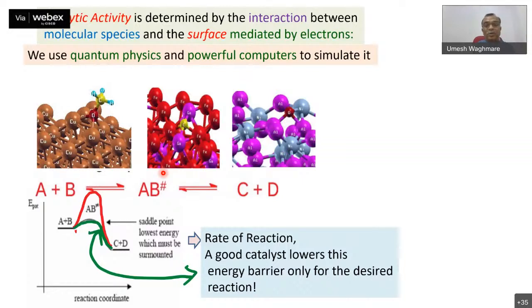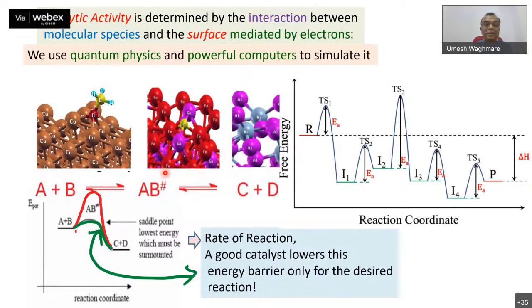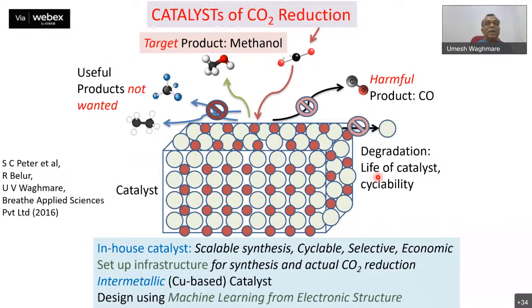This is a very simplified textbook description, but in a real catalytic reaction, there are several steps which go up and down, and from one step to another, one has to go through a transition state. So real analysis is much more complicated, and the catalysis of CO2 reduction is a very challenging problem because you want the target product to be methanol, not other products. One can easily get carbon monoxide by reduction of CO2, which is not a favorable product. One can get other types of degradation of catalytic material because of CO2 and poisoning. One can get methane or ethylene, and none of these are desirable because we want a single product, methanol, and that's what is called selective synthesis of methanol.